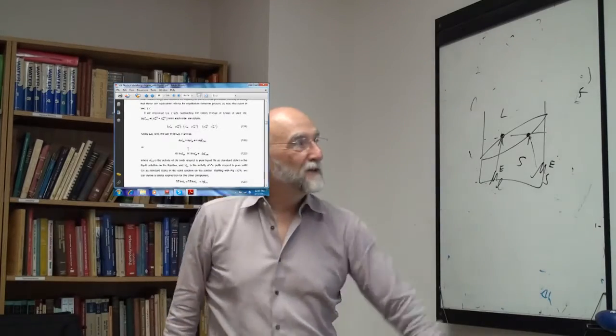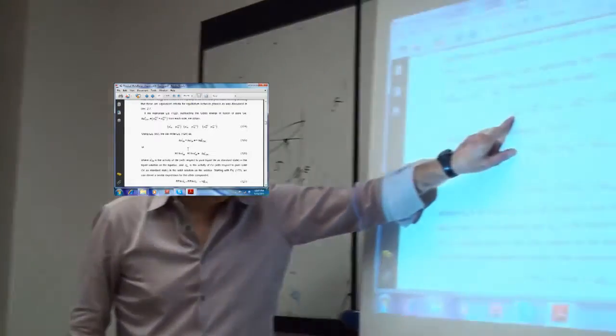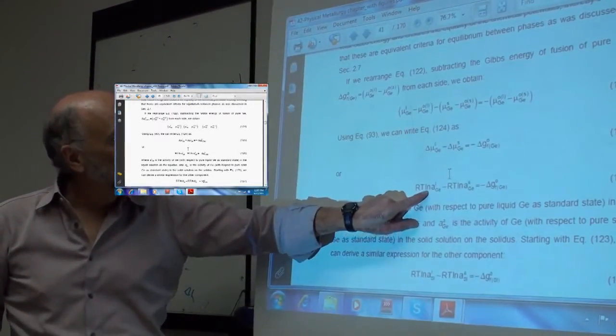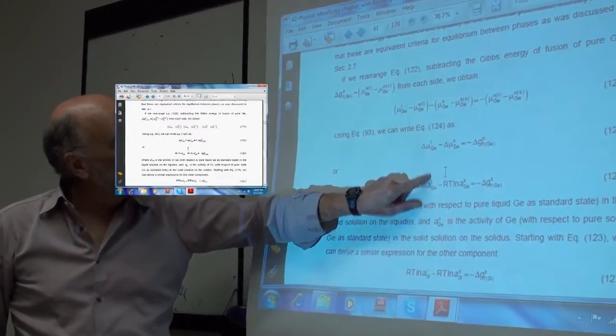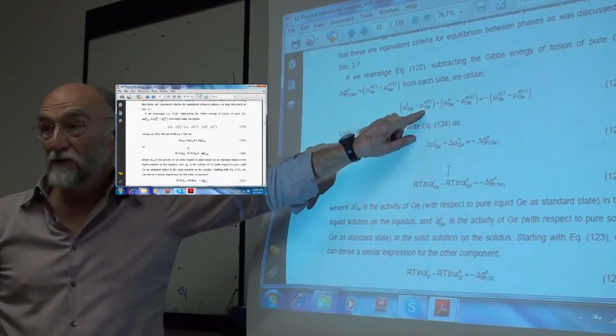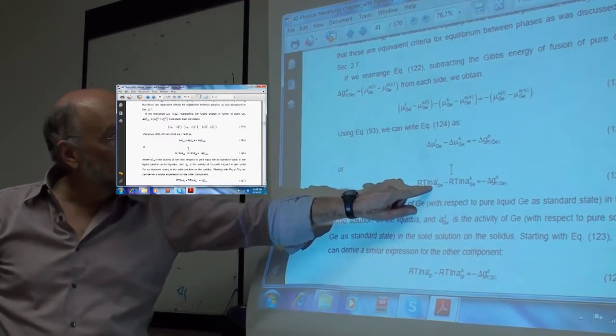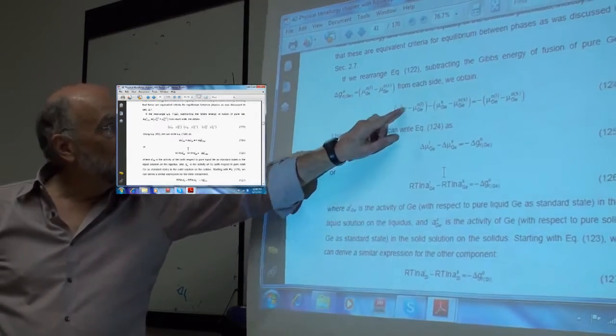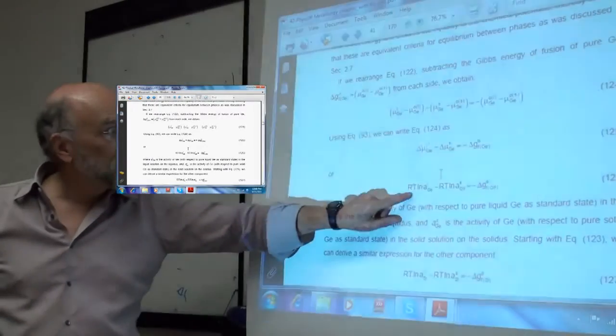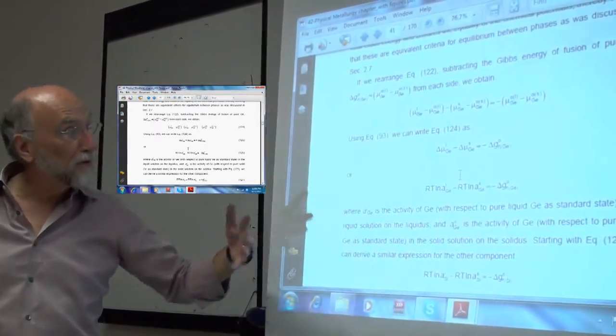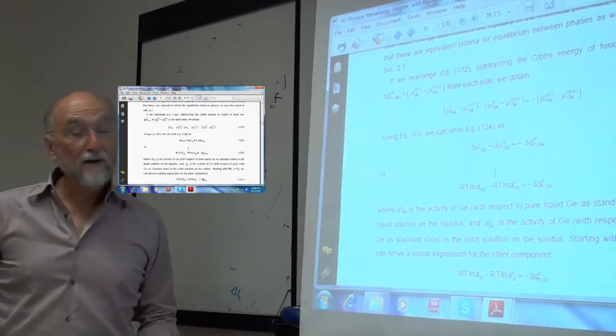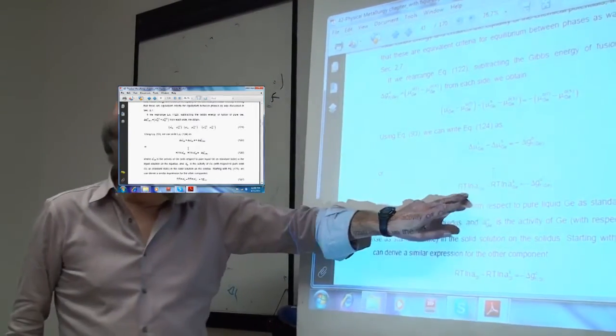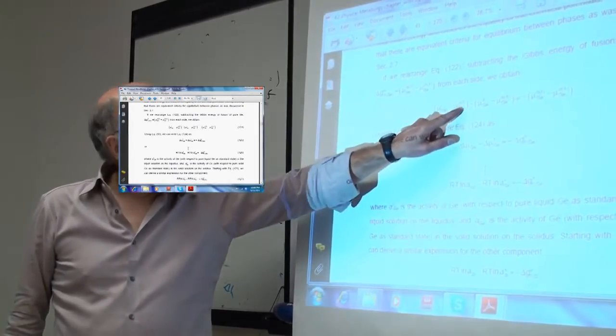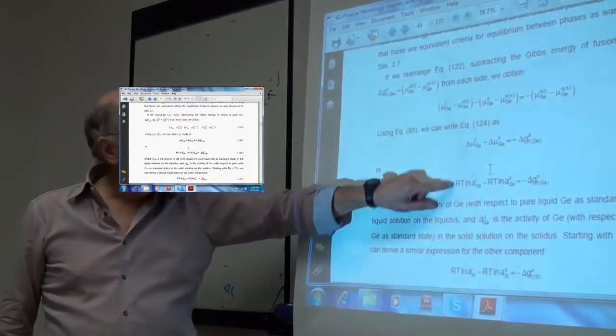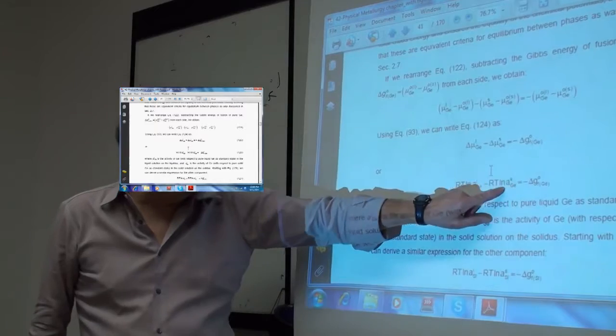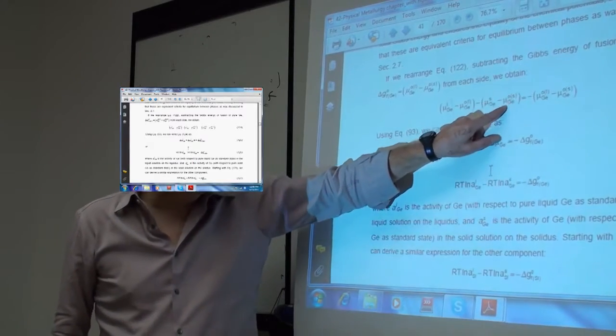Standard state. This is RT log, mu liquid minus mu naught germanium liquid, is the activity of germanium in the liquid state relative to the liquid standard state. And activity is always a relative quantity. It's mu minus mu naught. RT log activity is mu minus mu naught. You're always referring the activity to a standard state where the activity is 1. So this is the activity of germanium in the liquid, which means that the activity of germanium in pure liquid would be 1. This is the activity of the solid, germanium, in the solid relative to the solid standard state.